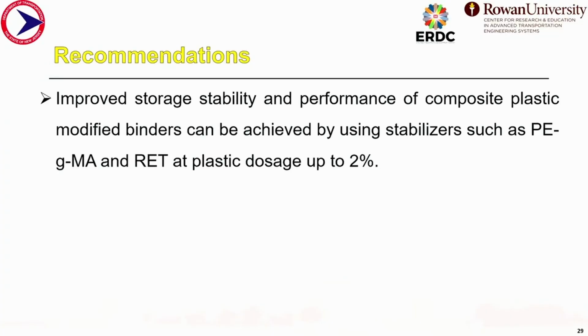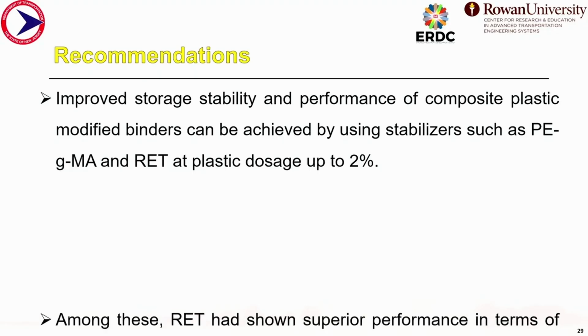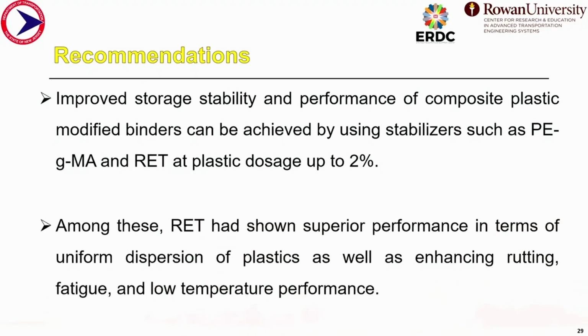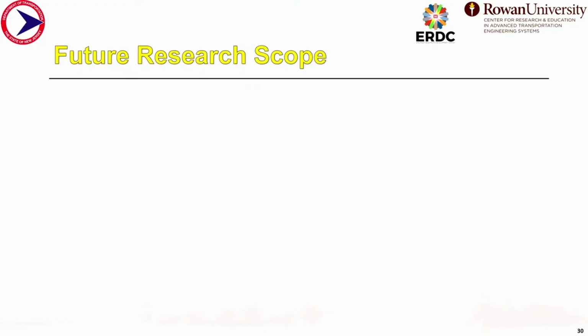As a recommendation, we can say that the improved storage stability and performance of composite plastic modified binders can be achieved using stabilizers such as maleic anhydride and RET up to 2% of plastic, whether it's mixed or single-use plastic. And among these, RET has performed better compared to the plastic modified binder and the binders with plastic and maleic anhydride.